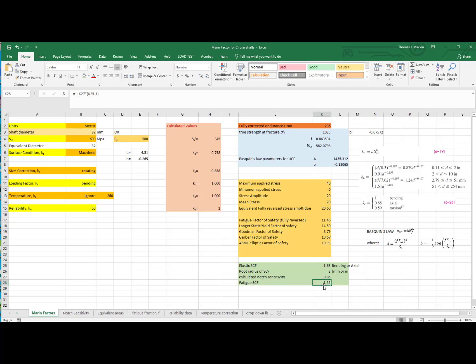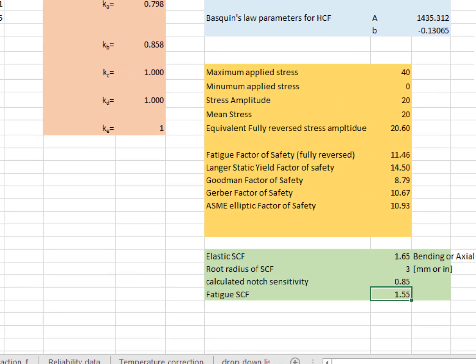So in the example that I'm showing right now, I have a shaft that's measured in metric units with 690 MPa ultimate tensile strength. I am imagining that this is a rotating bending sample that has an elastic stress concentration factor of 1.65. I put a notch root radius of 3 millimeters in it. I calculate my notch sensitivity to be 0.85, and that gives me a fatigue stress concentration factor of 1.55.